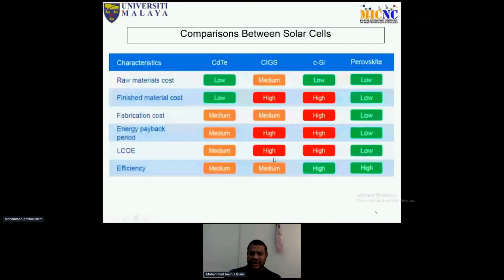So also you have a comparison over here. You can see now it's clear to you. If it is cadmium telluride, CIGS, crystalline silicon, which you call the wafer-based one, and perovskite, you see when you compare efficiency, both are medium, while crystalline silicon at 25% is high, and perovskite, above 25%, is also high. But when you go to the cost-related factors, that means raw material cost, finished material cost, fabrication cost, energy payback period, and the levelized cost of electricity, crystalline silicon has only a low raw material cost and the others are very, very high. So we are now using it, and 80% of the market share is dominated by this type of silicon. From here also you can get an idea: if we succeed in making perovskite stable, there will be a revolution in the renewable energy sector.